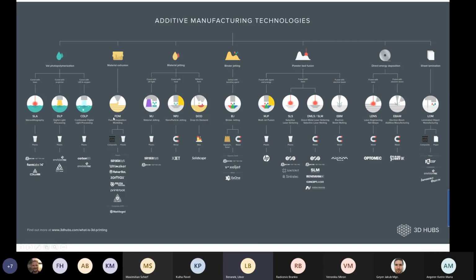A lot of technologies for FDM can work today also with metal materials. Then we have a part in a state where there is still a high percentage of some kind of polymer or binding agent, maybe with 80–90% of the metal powder. Then we have to add the process of sintering, where we basically get rid of the organic material with very high temperature. And because there is usually something like 10–15% of this binding agent or material which holds the powder together, the parts change their dimensions quite significantly during sintering, again 10% and so on. So this is a technology which is very close to metal injection molding, which is again quite an old technology.